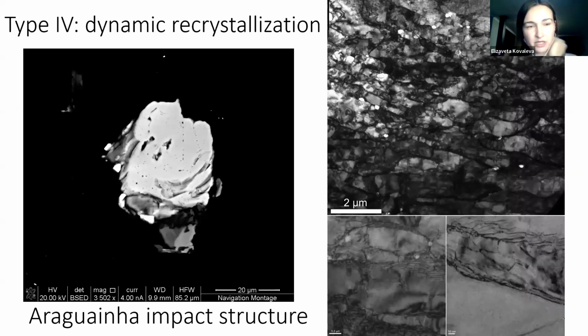I'm going to skip the other types because I think we are running out of time. This is just high differential stress, and this is actually a single crystal, but it is composed of subgrains, which are not quite new grains, but disoriented areas, domains of this initial crystal, which have a very interesting fractal kind of texture, where a large one is surrounded by smaller ones with the same shape.